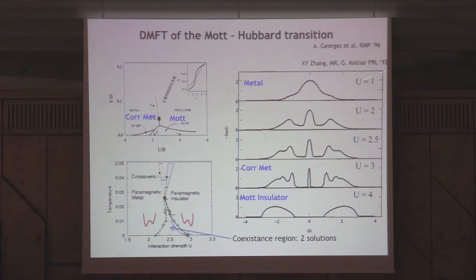So there you have the weak coupling limit with a small value of u, and what you see is that this metallic band is just slightly distorted by the emergence of some spectral wave that is being pushed at higher energies. As you crank up u, you see that this thing is really emerging as two wings, the lower and upper Hubbard band that start gathering much of the spectral weight.